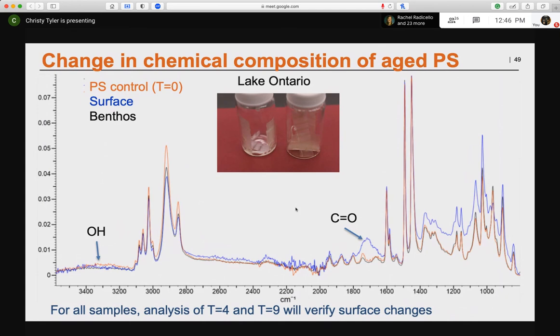And now this time it's being at the surface rather than the benthos. If you really look at the surface samples, you see no differences between the pre-deployment spectra and the spectra that we see after a month of aging. We still need to see the T4 and the T9 or T12, depending on how long the last one's left out there, to really see how this chemical is changing. So that's very preliminary, but we can also see that down at the lower wave numbers, we're seeing some changes in the spectra as well. So we're definitely seeing surface changes of these.